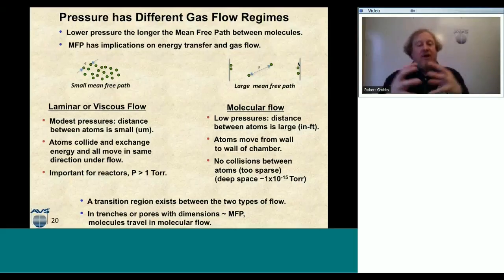Now, we've got our laminar flow and our molecular flow, and those are the two extremes of flow. But there's also a transition region, and this exists somewhere between maybe 250 millitorr down to maybe 20 millitorr. This is a transition region that I would encourage you to avoid when you're running your ALD reactors, because it has this turbulent flow, and it really can't make up its mind whether it's a viscous flow or a molecular flow, and it's a very challenging area to perform chemistry. But sometimes reactors need to be driven down just to the hairy edge of that transition zone in order to get our ALD chemistry to occur.